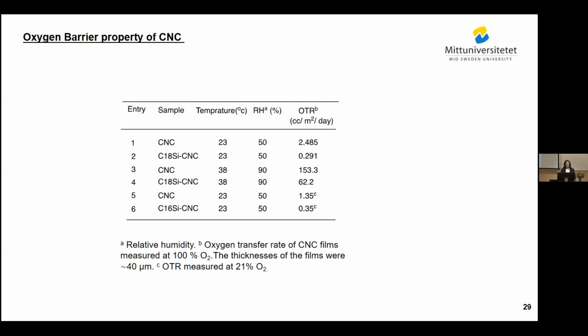Then we thought that if we check the barrier property after modification, it would be a valuable result, because we know that it's highly moisture sensitive, and in high relative humidity it can reduce the oxygen barrier property, and it doesn't have a good barrier property for water vapor. Then we measured the OTR, and the results show that at 50% relative humidity we could improve the oxygen barrier property when we modified with the C18. And even with this modified material at 90% relative humidity, we again have a good, improved OTR value.